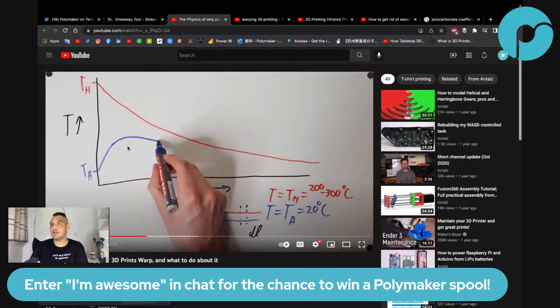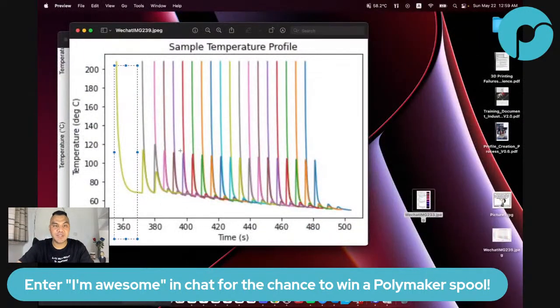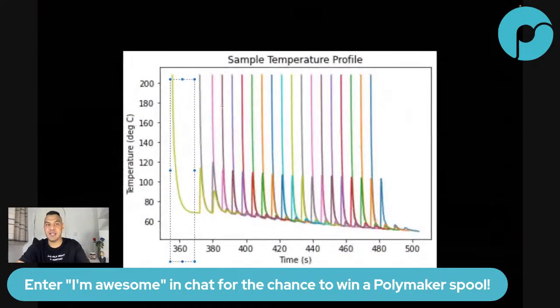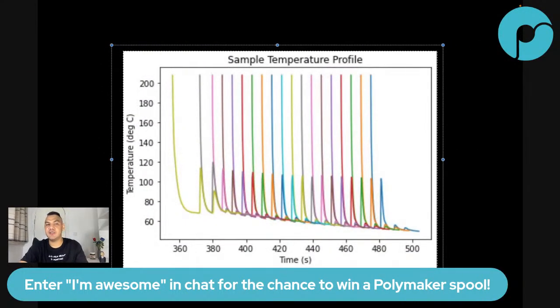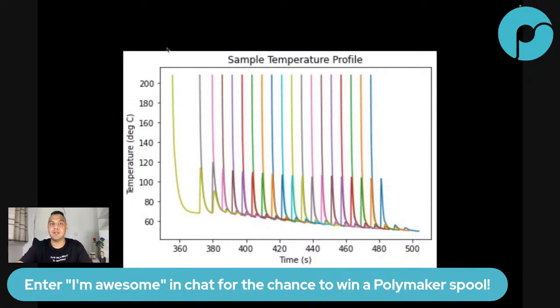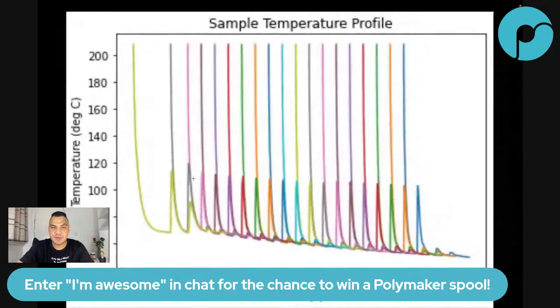Do you agree? So this is the part that is not right, because the whole explanation after that is based on having that gap all the time. But that gap doesn't exist. And if we go and check the simulation, that's exactly what is happening. This simulation was made by Helio Additive. Helio Additive has the best simulation software for FDM, and this has been proven. I can get the experimental data, but I did that on a short notice. But at least I have the simulation data. And this is exactly what's happening.